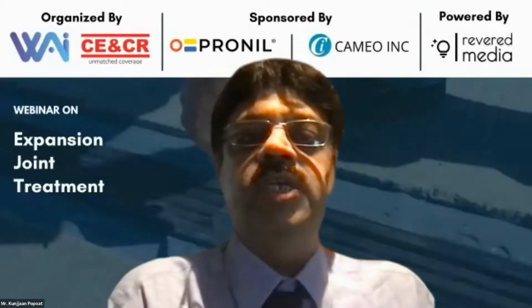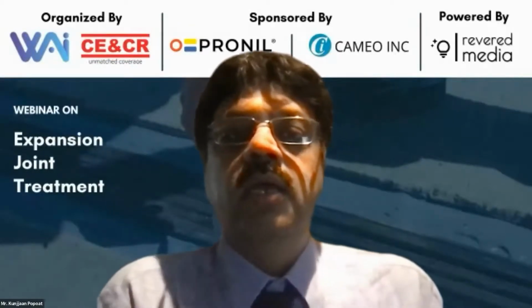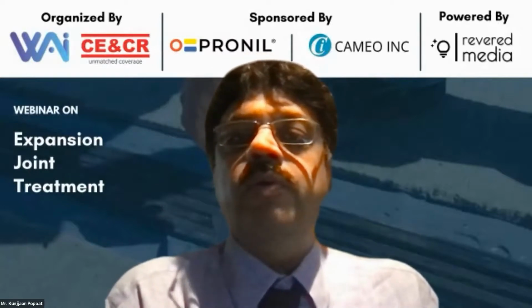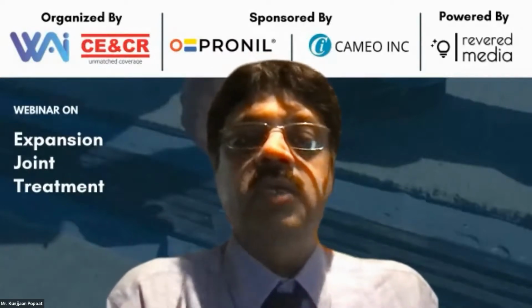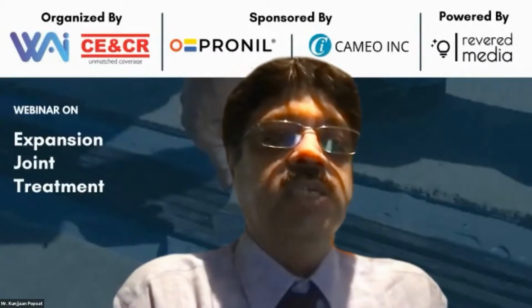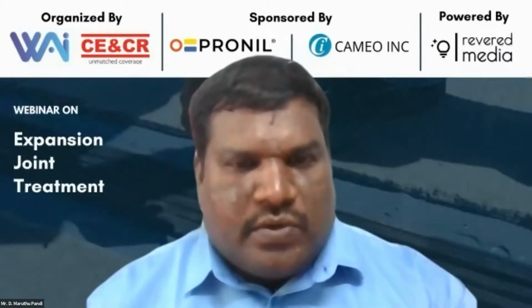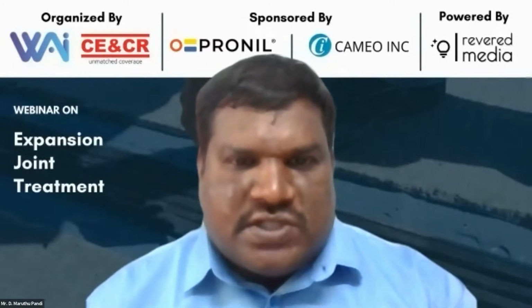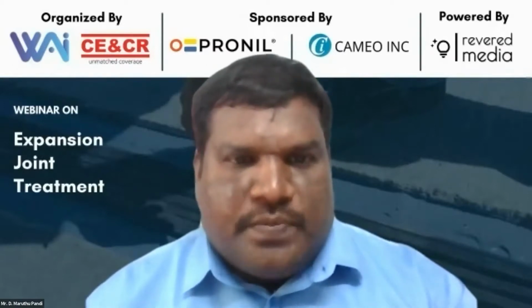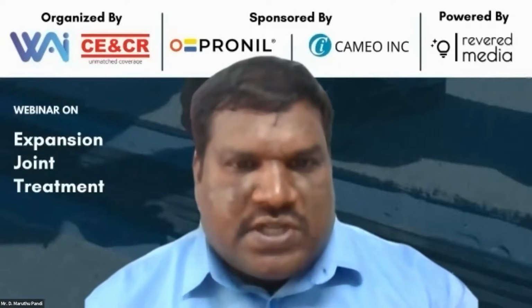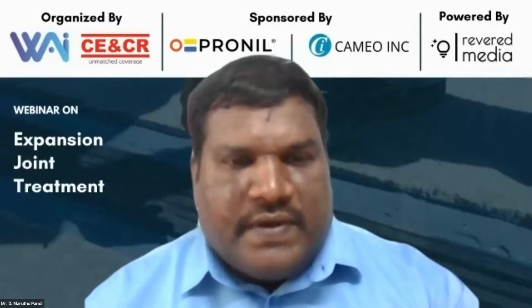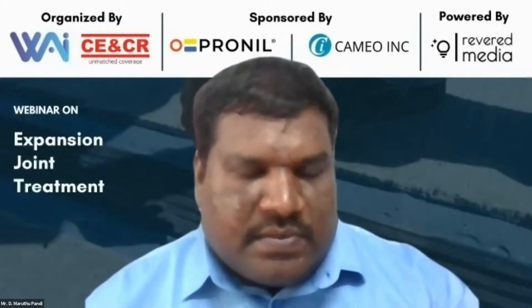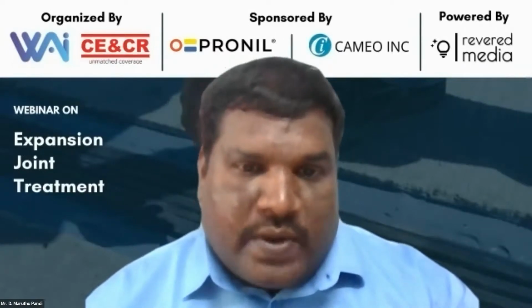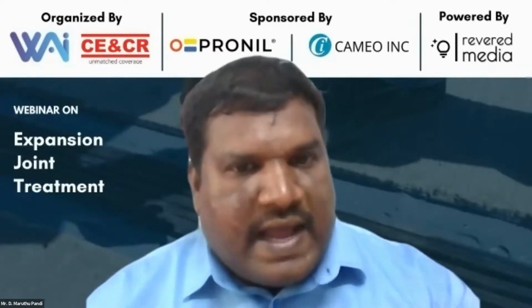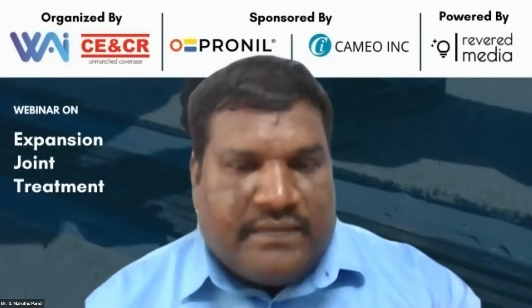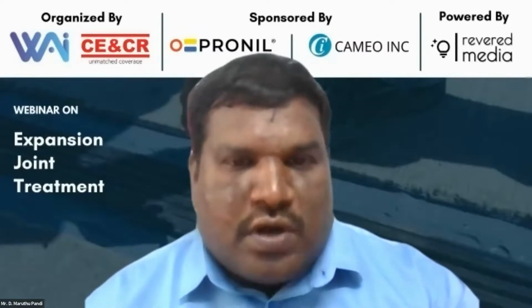There's another question, from Mr. T.G. Chandrasekhar. Does the tape require protective plaster? No, you cannot plaster it. You cannot put any rigid material on top of the expansion joint because it has to breathe. Expansion and contraction should happen. If it is any rigid material, actually a non-woven is required on top of the surface to have a plaster or a concrete, but where the expansion contraction area should not be closed.